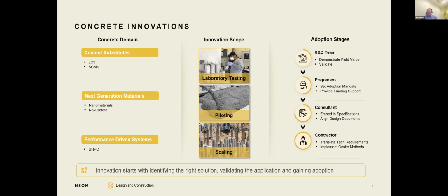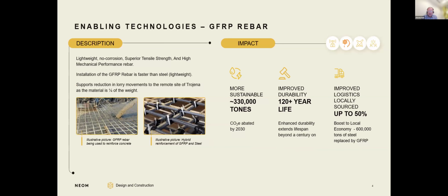I just wanted to briefly talk about enabling technologies, because GFRP has been an interesting piece of work, and it leads into my next slides on codes and standards. But GFRP really, as a polymer-based reinforcement, is an enabling technology that's allowed us to work in a consortium on developing a saltwater concrete that doesn't use potable water, so that we're benefiting from not using precious resources of fine sands and potable water. We're able to use seawater. We've seen substantial CO2 reductions in the use of the technology, and we are deploying it in a number of our applications. And the numbers that you see here in terms of CO2 abatement are for very, very small substitutions.